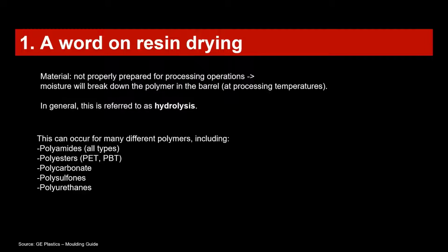Otherwise, such polymers react with the moisture at the processing temperatures, and when this reaction occurs, the polymer chains break, and this results in loss of properties. And also when you have the moisture itself in the part, it can manifest itself as splay and silver streaking, blisters, and has of course an impact on the cosmetic and physical properties of the components. So therefore it's really essential to ensure the optimal removal of the moisture in the final part.